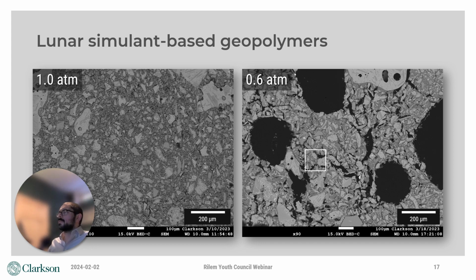The image on the right is lunar concrete formed at reduced atmospheric pressure. The lower pressure means the air bubbles don't collapse. Instead, they remain in the microstructure as it hardens, leaving the very large air voids you see here. These air voids dramatically weaken the strength of the material, which is yet another challenge we need to overcome.